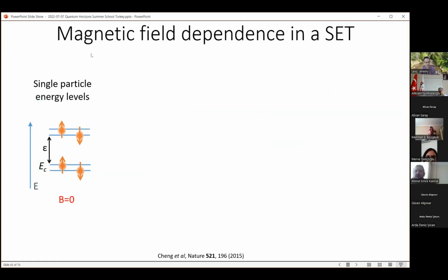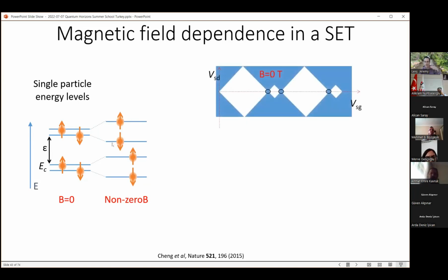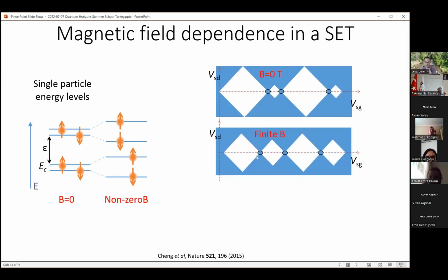So the other thing that can happen is that a magnetic field can Zeeman split the energy states, and so that will cause a shifting of these levels up and down, and it will impact the shape of this structure by moving these points to the left or to the right. So this one would move, let's say, to the left, this one would move to the right. It would cause the diamonds to grow and shrink in size, but you wouldn't see, for example, a change in the number of intersection points. And you can trace these points as a function of magnetic field.